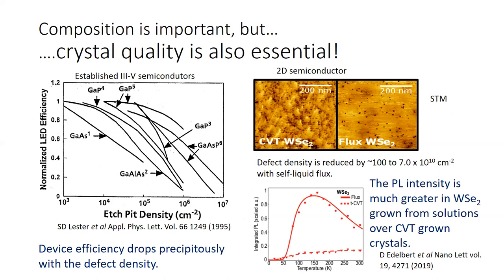So I see a lot of papers where people look at composition of the films they've grown, and certainly composition is important, but crystal quality is also essential. And this is one of my career favorite plots. It shows the efficiency of light emitting diodes as a function of etch pit density. Etch pit density is associated with defects in the material. And what you see is that defects really kill the device efficiency.